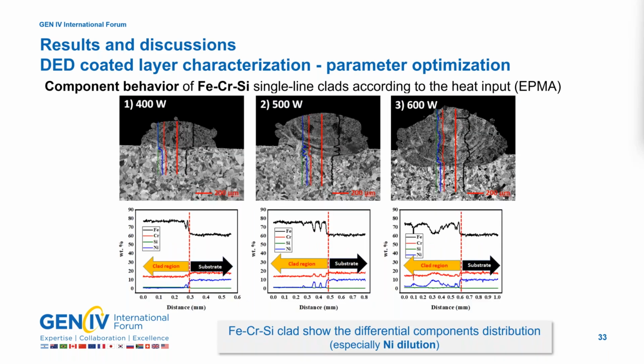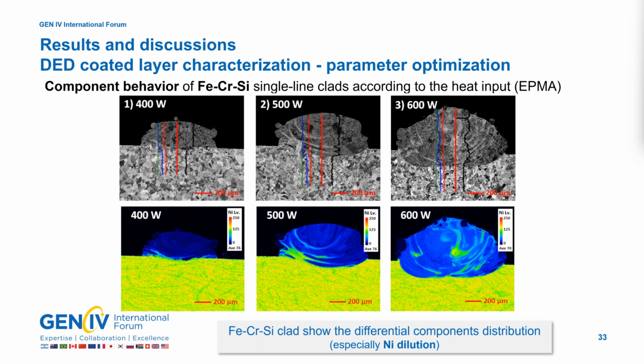On the other hand, in case of iron chrome silicon, differences from the substrate composition were expected, but differential component distribution was observed even within the melt pool. In particular, the dilution of nickel, which was present in the base material, was observed locally.